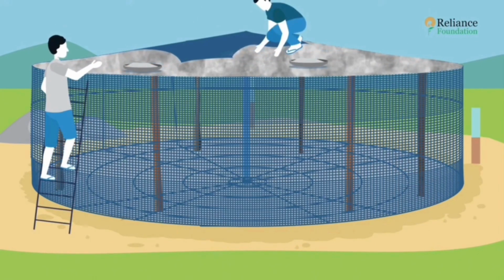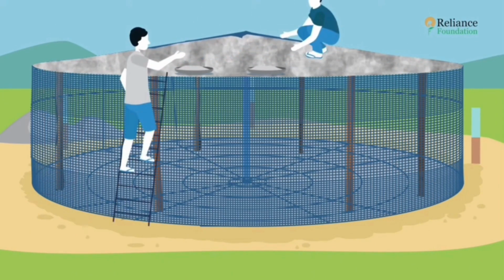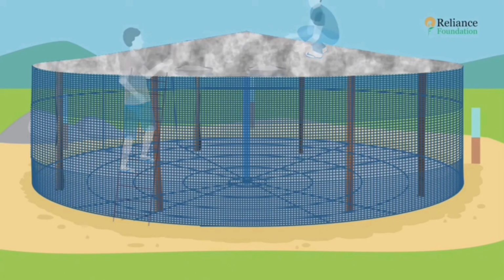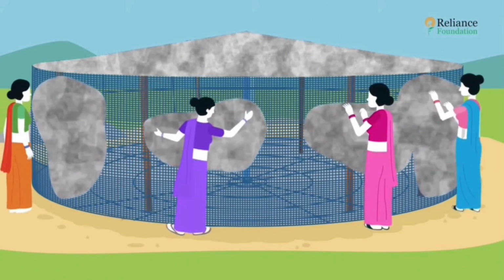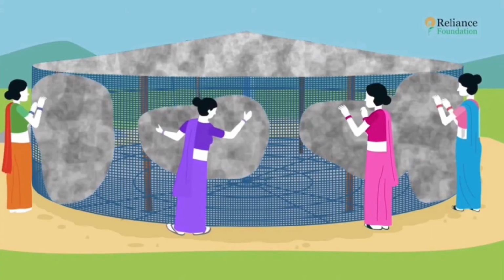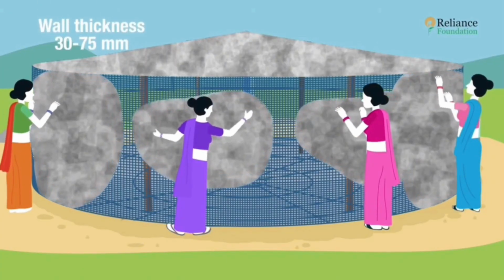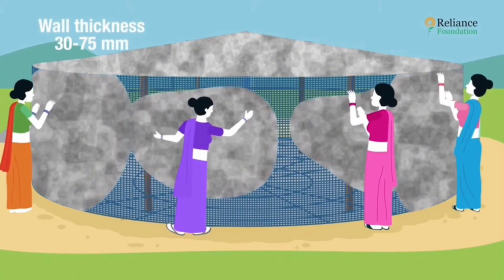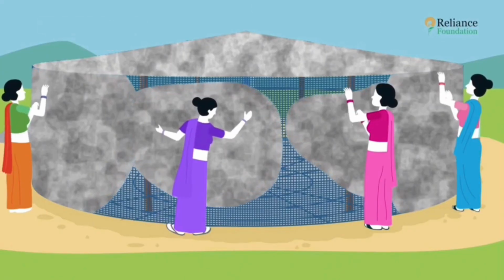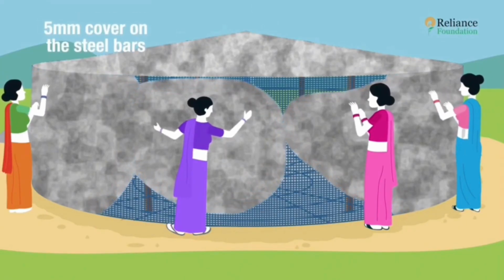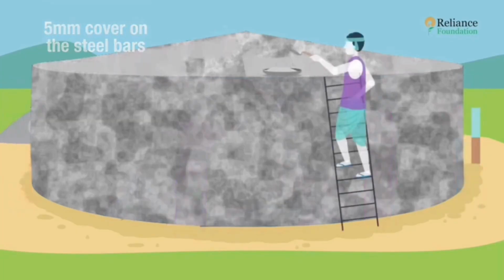You will see that the mesh does a good job of holding the mortar in place. Since this process is basic, anyone from the community can participate. The wall thickness should be between 30 to 75 millimeters, depending on how much is needed to have at least a 5 millimeter cover on the steel bar.